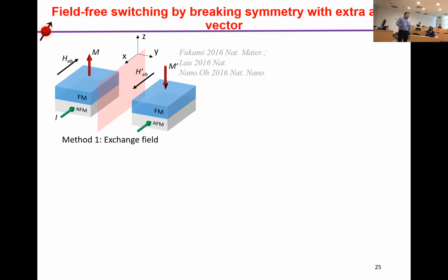Actually, the community has proposed a lot of methods. The first one, antiferromagnetic materials coupled to ferromagnetic materials, which generate a unidirectional anisotropy. This unidirectional anisotropy shows exchange bias in the MH loop. This exchange bias behaves like an external magnetic field, so it breaks the mirror symmetry. So based on this method, we can switch the magnetization deterministically.